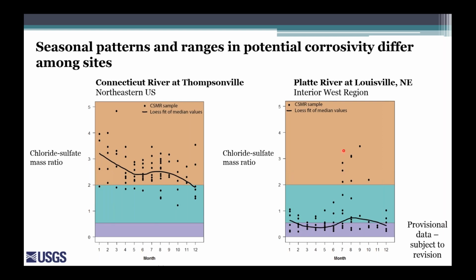But one thing we do see is that in late summer, there is a collection of very high observations with chloride to sulfate mass ratios well above 2. These particular observations coincided with the very severe drought in 2012. And so in this case, they seem to be related to a hydrologic event rather than to the use of road salt, as we saw in the Connecticut River. So the Platte River is really showing us something different. We're seeing a different process that's leading to potential corrosivity in the surface waters, and we're seeing a difference in the timing and a difference in the regularity of something like this.